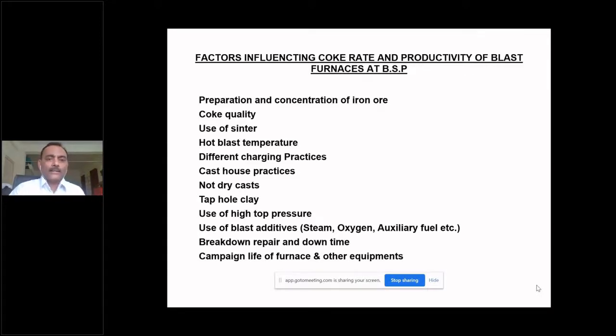When you remove the metal and slag from the cast house, what type of practices are involved in the cast house? Not dry cast means whenever you open the cast, all the liquid which is inside the furnace should be completely removed, and then tapping should be closed. So dry cast is avoided. Taphole clay: as the very high temperature metal and slag continuously come out of the tap hole, the clay through which the tap hole is closed, if it erodes, quite naturally we are not able to drain all of the hot metal and slag from the furnace.